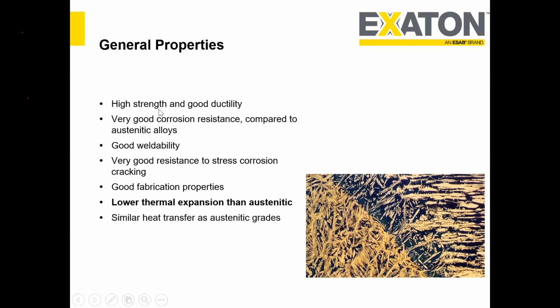So it gives very high strength and good ductility. And with higher alloy elements, which means a higher grade of the duplex family, from lean duplex to duplex to super duplex to hyper duplex, the strength, in terms of both tensile and yield strength, gets higher and higher. At the same time, the corrosion resistance also increases. So in general, between austenitic stainless steel and the duplex family, duplex is always better in corrosion property. Just take note that austenitic stainless steel 316L and lean duplex 2304 or LDX 2101 have similar corrosion property. And actually lean duplex was developed to replace stainless steel.